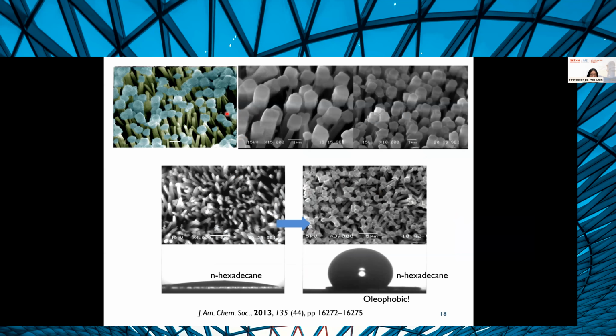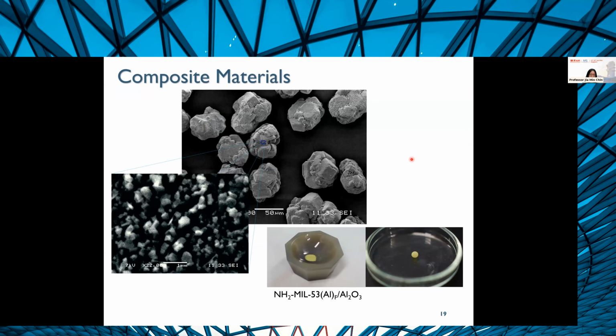And you see here that if you leave it a little bit too long, you end up with these MOF lollipops instead, because the liquid layer starts to crawl up these microneedles. But this was a fun little example for us of showing how one can exploit liquid-air interfaces to control growth. We then looked at some other composite materials.